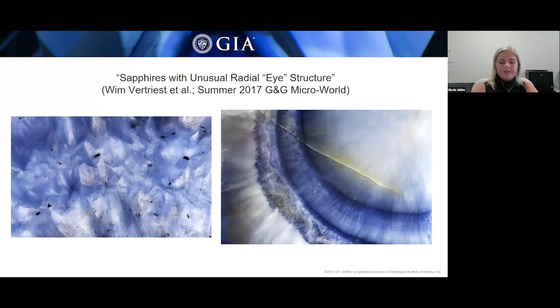Raman spectroscopy confirmed that both the blue and the white areas were corundum. Diaspore, which is a common secondary mineral found in corundum, was also identified in the white areas. ICP-MS was performed on the stone pictured here, and it was revealed to have very low iron content, so it is presumed to not come from a magmatic source. It should be pointed out that this stone was not subjected to heat treatment, because corundum heat treatment is a common practice and it is accepted in the trade.